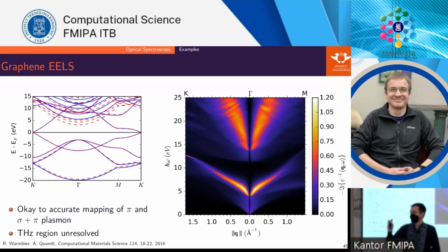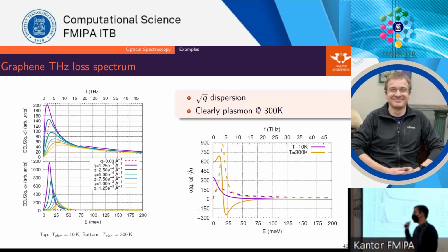Right. Okay. Here is an example of how this looks in graphene. In graphene you can excite, for example, in the ultraviolet, 5 to 10 electron volts, depending on the momentum, and there's another excitation you can do around, say, 15 to 25, and these involve different electrons in the electronic structure. That is actually very similar to the behavior of graphite. It's kind of standard. That calculation also took about a month to get that one picture.